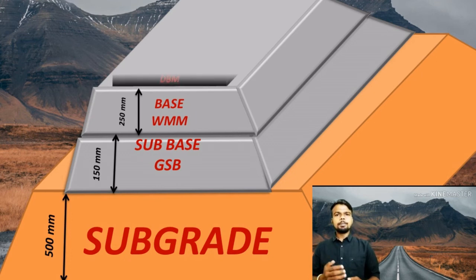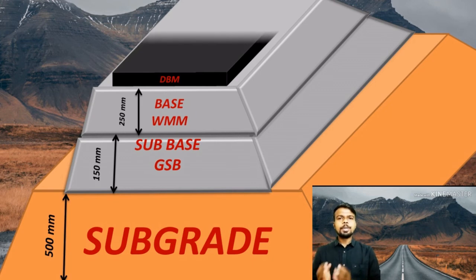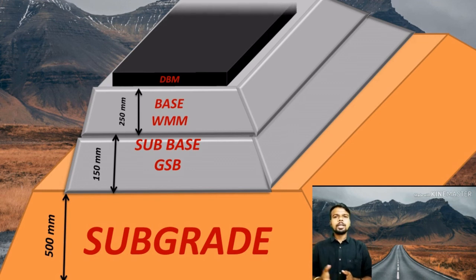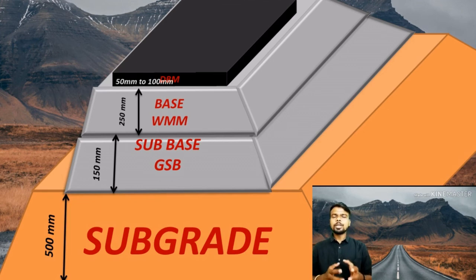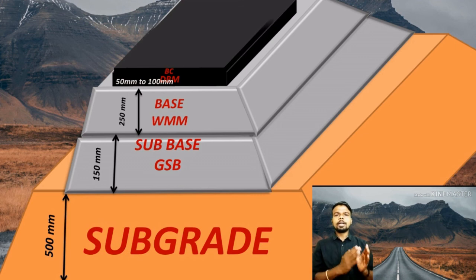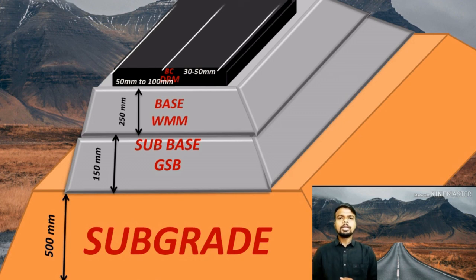The bituminous layer consists of bituminous surface course, bituminous base, and bituminous binder course. It is divided into two parts: DBM (Dense Bituminous Macadam) and BC (Bituminous Course). The thickness of DBM varies from 50 mm to 100 mm, and the thickness of BC varies from 30 mm to 50 mm according to design traffic volume. There are two grades of bitumen used: VG30 and VG40, selected as per design traffic volume.